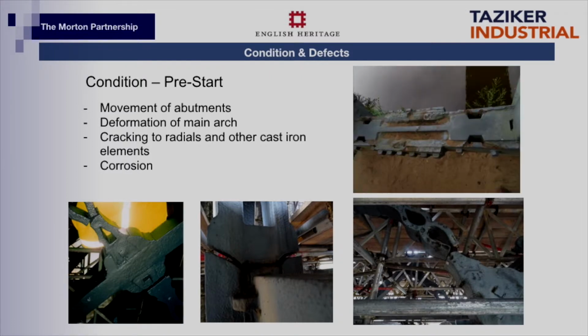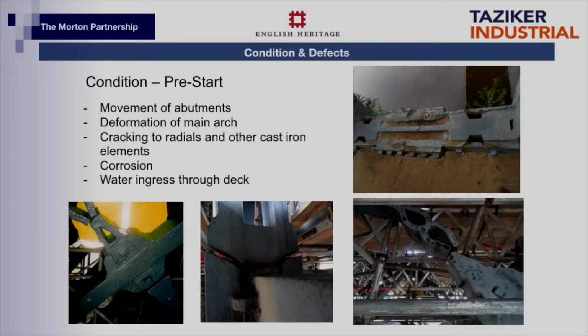And corrosion, a big part of it, and at the top there you can see some of the 1902 repair straps. So that's another thing that came clear fairly early on, that there was a whole series of later repairs. It's recorded the first repairs were only 3 years after it was finished, and that's due to the gorge movement. And the other key one was water ingress through the deck sheets.